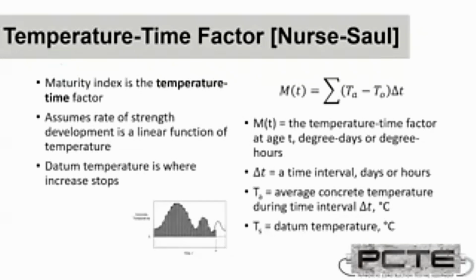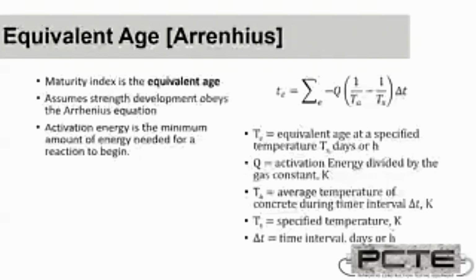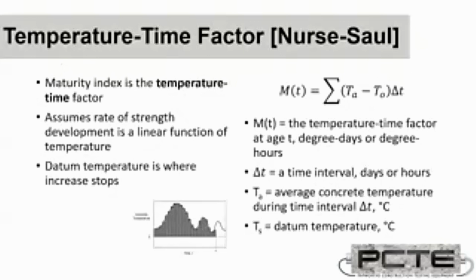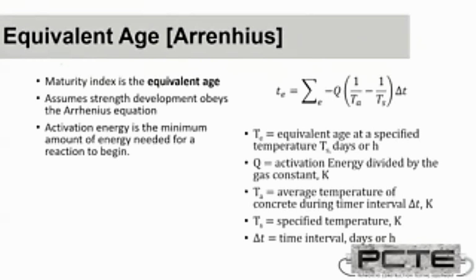We're using an equation that models concrete strength gain, and our curves and our relationships are based upon this mathematical model. So when we're doing things like confirmation breaks, we're confirming that our mathematical model matches the real performance, the real chemical performance of that material. And there's two assumptions that go into that. It's the datum temperature for Nurse-Saul and the activation energy for Arrhenius. And again, your ASTM standard defines the calculation, the formulas, the additional laboratory procedures to establish those fixed criteria, and the confirmation.